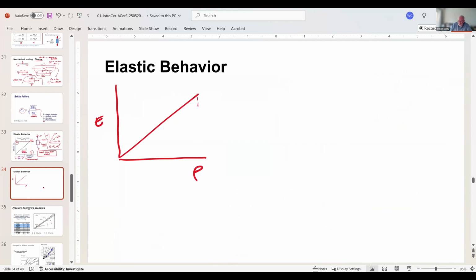Now, if I get to my peak density, this is my density max. So fully dense ceramics, for example, this is my elastic modulus max. This is just the elastic modulus of the material. Here's the problem. People like to take this value and apply it, ignoring the change in density. So if I sinter the material, I may start down here. This is my dry ceramic component. Look, at that density, this is all densification. But I have a low elastic modulus down here. That's fine. So as I densify the sample, elastic modulus goes up, and it goes up linearly.